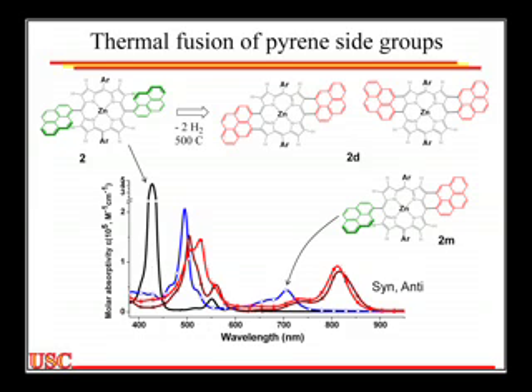But the key is, this is all great, but remember, I don't care about any of these photons. Right? If I were to make a solar cell with this one that's absorbing out to 1200, my open circuit voltage might be 50 millivolts or something. I'm going to thermalize all the way down to here. The highest efficiency solar cell I'm going to get in a single junction cell needs to have an edge right here at about 950 nanometers. So even the dimer is already too red to use in an efficient single junction solar cell.